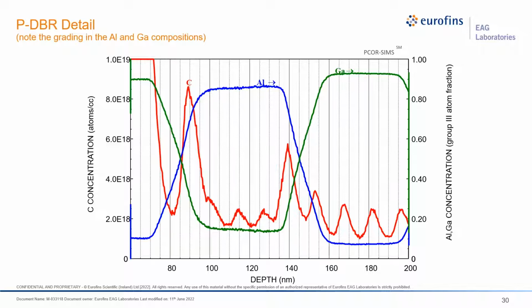Further reductions in resistance of the P-type DBR are possible by doping the mirrors with carbon, which has a sensitivity that is significantly affected by alloy composition. However, with PCOR-SIMS, we can correct for these effects at every data point. That's very important, at every data point, because the aluminum composition is measured for every carbon data point. Such an approach uncovers a high concentration carbon doping spike in some structures, which is near but not exactly at the interface. And you can see that here in this slide.